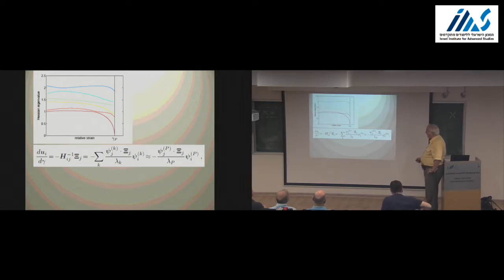And now I can take the psi, it's a nice vector, I can expand it in the eigenfunctions of H_ij. So I'm expanding in psi_k, okay? This is psi_k dotted onto psi, the amplitude, and this is the eigenfunction itself. Since the eigenvalues now appear in the denominator, when one of them goes to zero, this sum is going to be dominated by the one associated with the lowest eigenvalue lambda_p. Therefore I can predict that my non-affine response is going to be proportional to the eigenfunction associated with this eigenvalue.